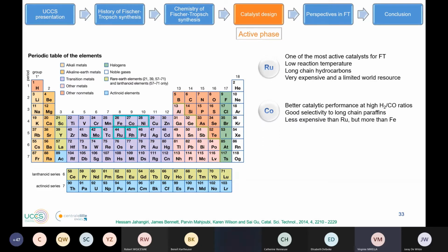Cobalt has good catalytic performance with a quite high ratio of hydrogen to CO. It also has good selectivity to long chain paraffins. It is less expensive than ruthenium, but a little bit more than iron. But for synthesis of olefin we are not going to use cobalt either. There's also iron. Iron works very well at low ratio of hydrogen to CO, and it is interesting for production of olefin and oxygenates. It is really economic, it's abundant, even if in operating plants, iron is less stable compared to cobalt. I mean, cobalt catalyst has a durability of approximately 5 years compared to approximately 6 months in the case of iron.